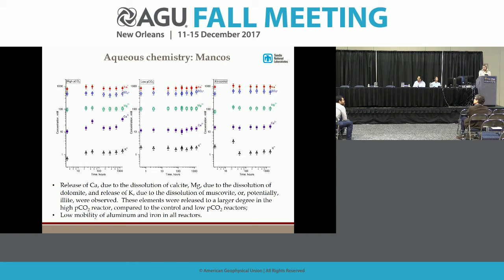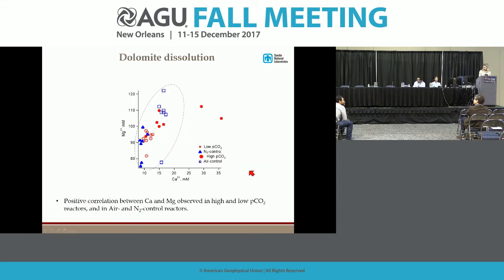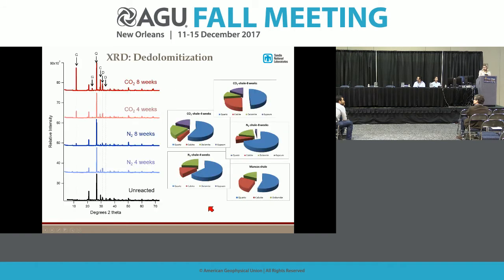throats and affect permeability. And again, another piece of evidence for dolomite dissolution is that when we look at magnesium versus calcium, we see a linear correlation. And the dolomite in our sample was actually a magnesium-rich member. When we sampled those reactors, we looked at both aqueous chemistry and the solid chemistry change at the same time. Here I'm showing results for the low pressure CO2 reactor, and we detected an interesting reaction going on. These are XRD patterns for four samples: unreacted, and then reacted under control conditions with nitrogen and under low CO2 pressure.